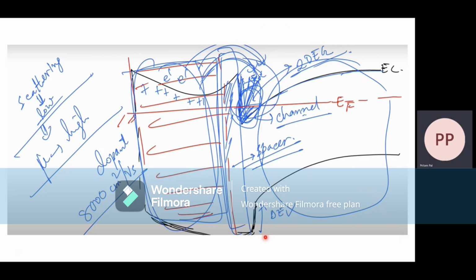But there's a special layer of a few nanometers that makes sure this electron gas, this channel, is physically separated from the dopant layer. This spacer layer separates the channel from the donors, so the scattering will be low. The scattering will be low, which means the mobility will be very high, and so we call it a high electron mobility transistor.